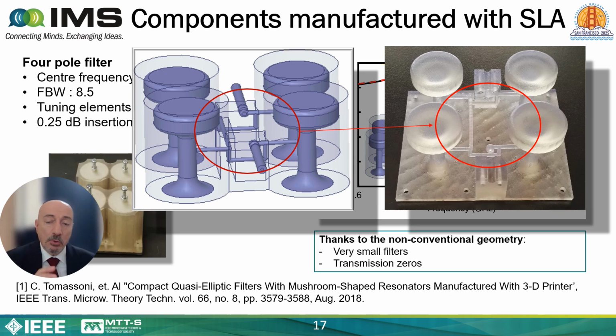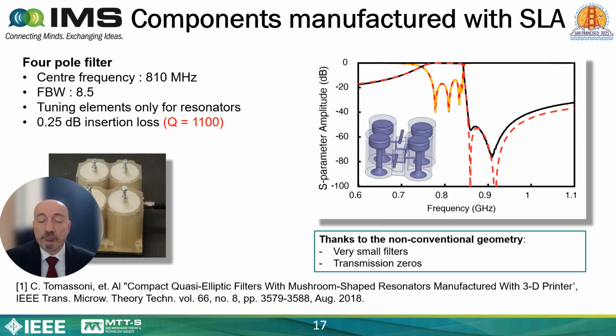And this is very important because if you are using a traditional technology for the manufacturing of this filter, for example, the drilling technology, well, in this case it is impossible to manufacture this in one shot. You have to have the base, and then to the base you have to add all the posts, and then you have to attach this complex network. And at the end, it is much more difficult, and there are problems with the accuracy. So in this case, this technology allows a lot of advantages.